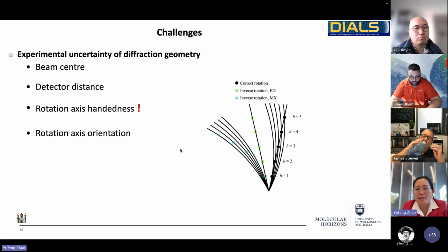There is also the handedness issue. I think we have some audience from the pharmaceutical industry, so handedness for pharmaceutical samples is a really crucial thing. For example, these black dots are nicely lined up reciprocal dots with the correct rotation axis. For X-ray crystallography, if you use an inverted rotation axis, you would get some arced data and you couldn't process it,